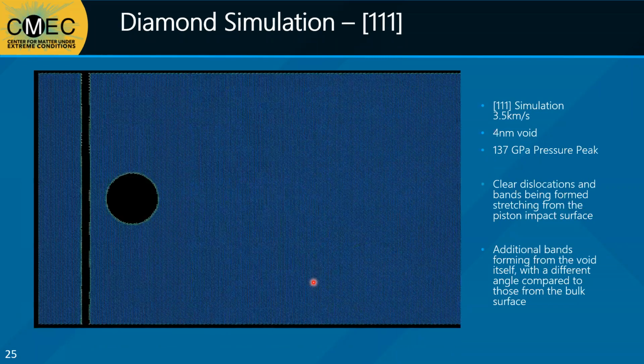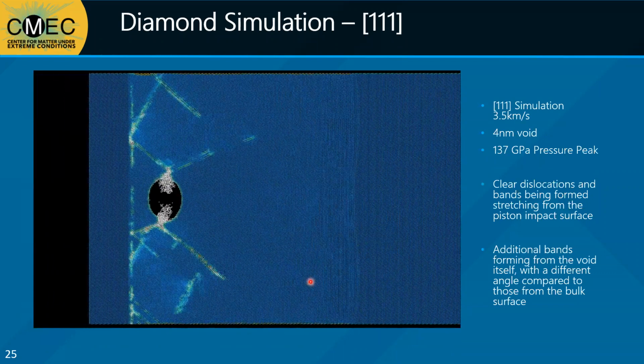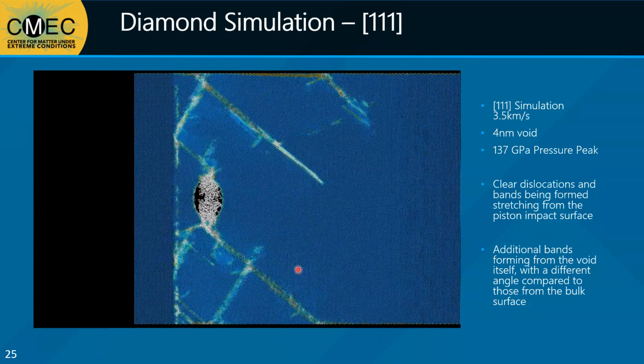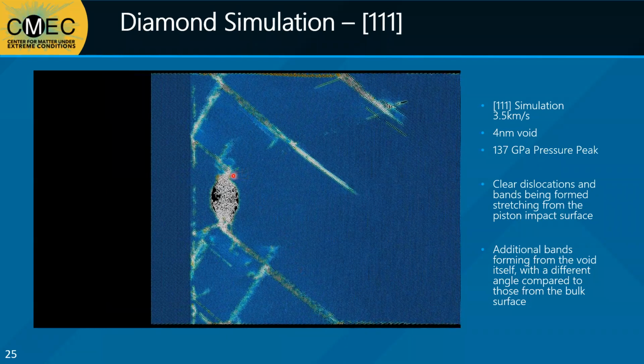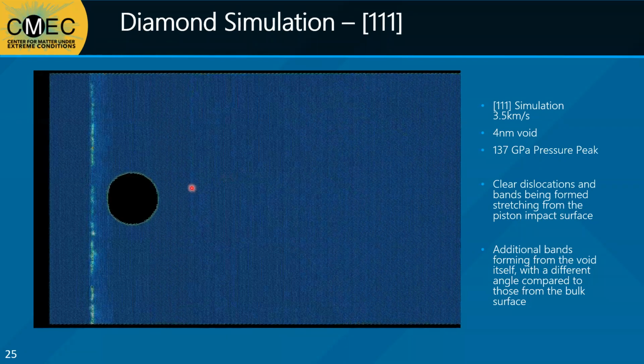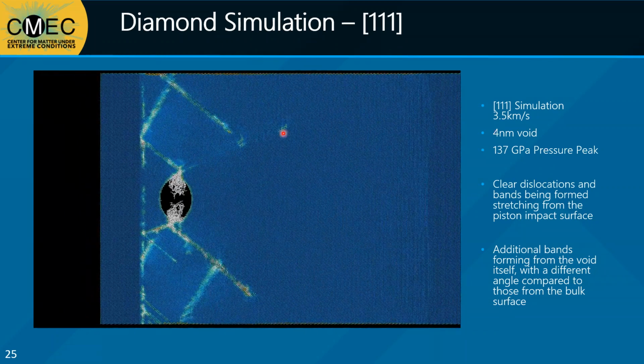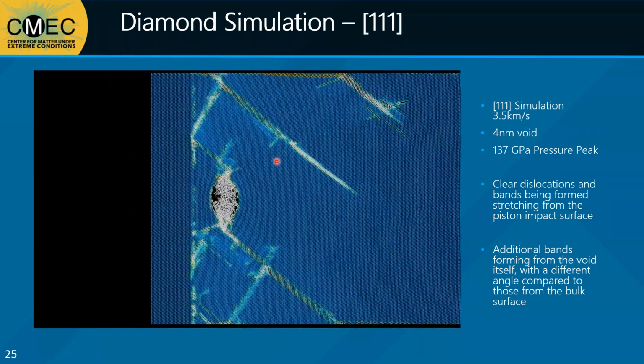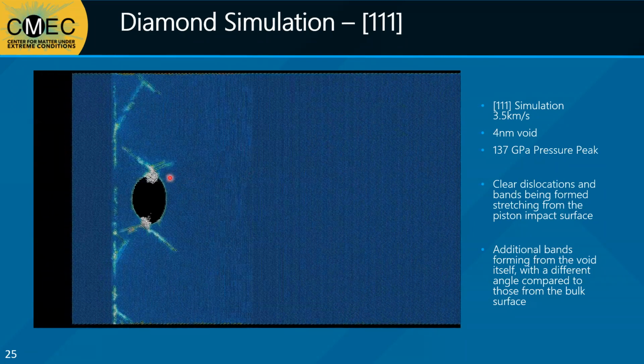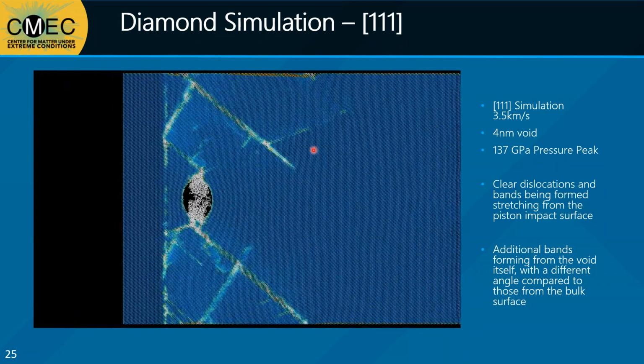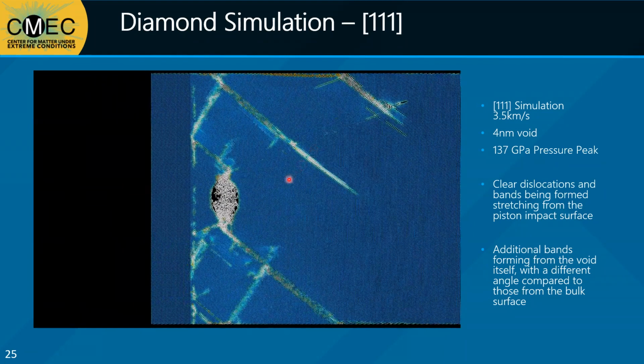When a void is introduced, even more interesting things start happening. In this 2D slice of the simulation, we can see that there is an emanation from the void that is at a different angle compared to the rest of the dislocations going through this simulation. In addition, it is not leaving behind a stacking fault in its wake. It is likely that this dislocation is another type of dislocation that is acting along a different slip system that was not present in our simulation where it was just a planar impact surface.